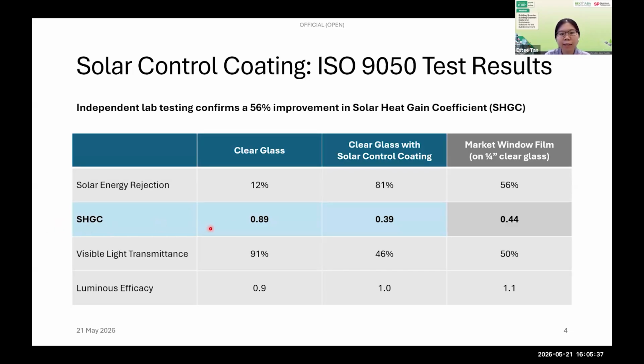The market film brings the SHGC down from 0.89 to 0.44, but the solar control coating goes even further to 0.39. So this means that at a comparable level of visible light transmittance, our solar control coating delivers better heat rejection.